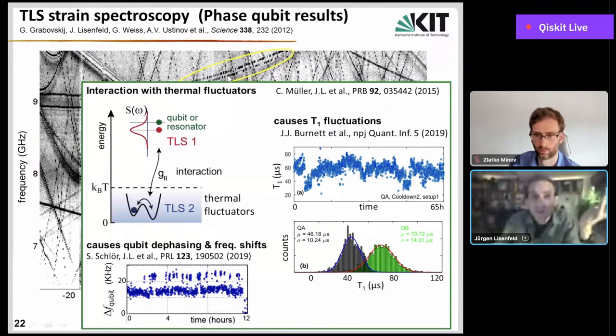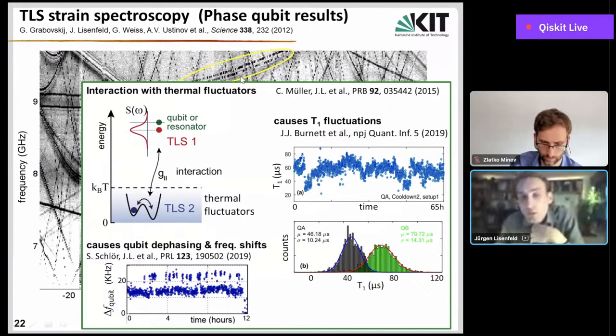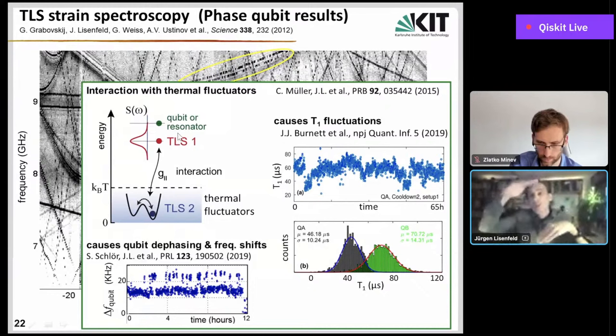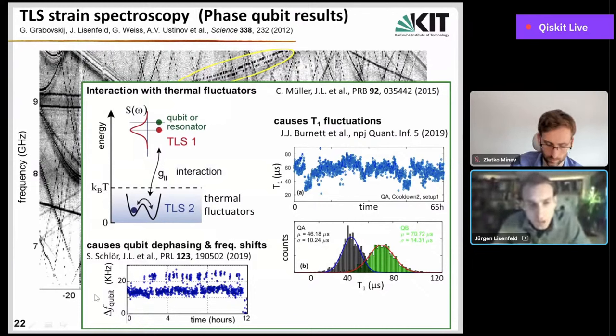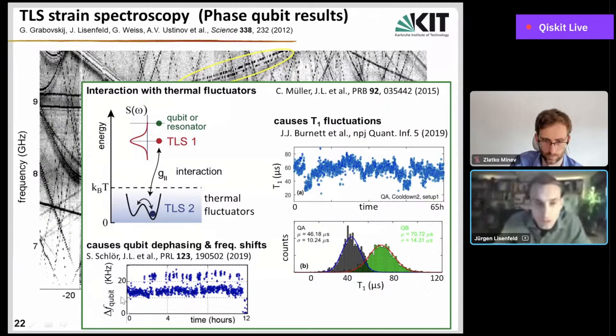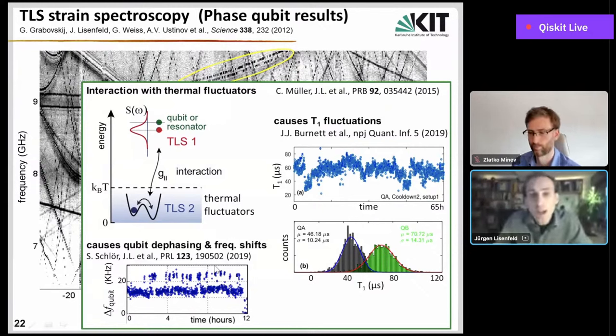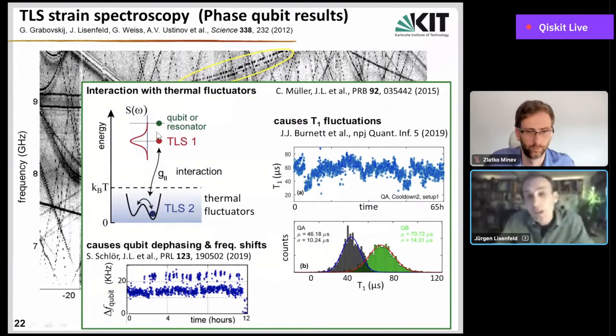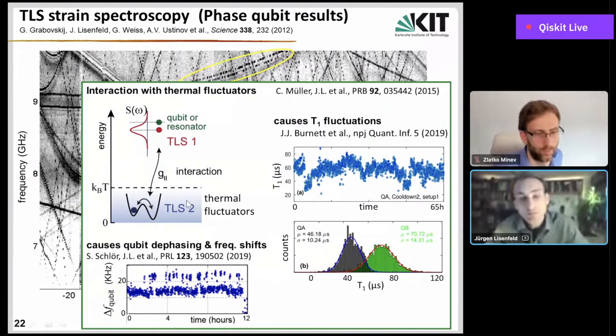Actually, this defect here kind of heralds the state of this thermal fluctuator. And this is, of course, very bad for a qubit, because you can imagine if you have a qubit in close vicinity to this defect TLS1, then you could, for example, assume that the qubit gets repelled always when this defect comes a little bit closer to the qubit by some kind of dispersive shift, if you wish. And this is also something that we found at some point. We measured the resonance frequency of a transmon qubit here for a long time, and actually could also identify these kinds of telegraphic switchings between basically two different resonance frequencies, most likely due to this interaction, in that the qubit saw this TLS1 fluctuating due to this thermal fluctuator here.